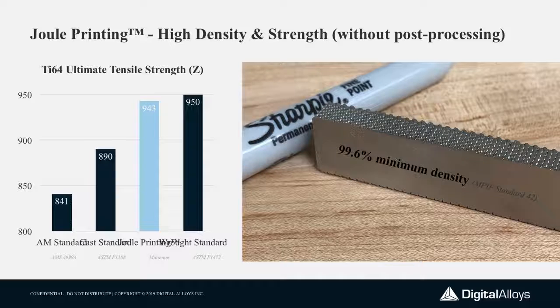We're seeing really high density, 99.6% minimum density, again, without post-processing. And what you get in terms of surface finish is similar to a sand casting, somewhere in the range of 50 microns Ra surface roughness. So it's a near net shape process in almost all applications, right? Think of it like casting. You're having to do some sort of finish machining to any functionally critical surfaces. But the benefit is that you can get to that near net shape very quickly, very efficiently, especially in materials like titanium, which are expensive, which are hard to process, which consume a lot of energy for material waste.